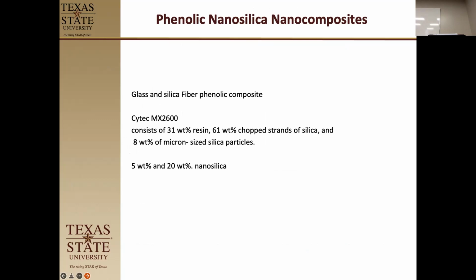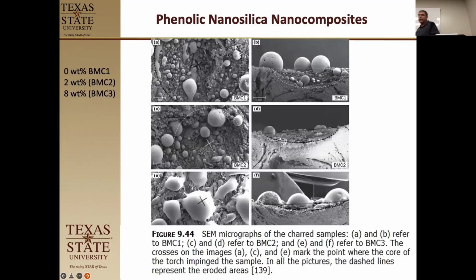They used a standard material, which is a commercially available material, 31% resin, 61% chopped strands of silica, and it also contained micron-sized silicon particles. But then they added 5 and 20% nanosilica, thinking that it would change the property, change the heat flow by having the nanomaterial in there. Okay. So when we look at this again, we see the glass fibers are melting into those little balls right here.